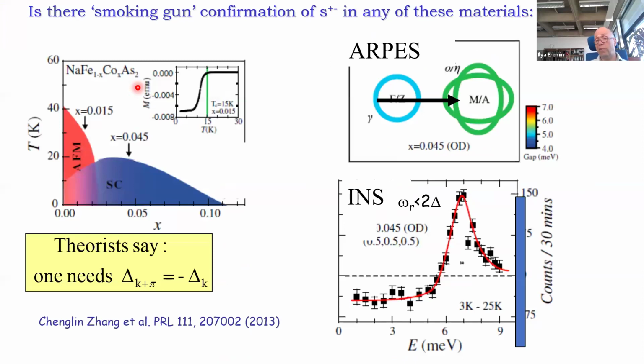There is one issue, however: there is still no direct evidence, in my opinion, that the superconducting gap is changing sign. In other words, there is evidence in my view, but you need to do some calculations. What you need to show is that once the superconducting order parameter changes sign, there is a claim by theorists that the Bogoliubov coherence factors, because you have Bogoliubov quasiparticles, will start to behave differently compared to a conventional superconductor.